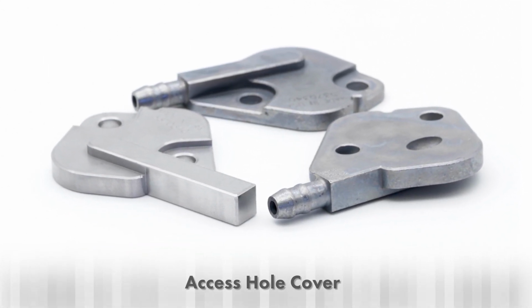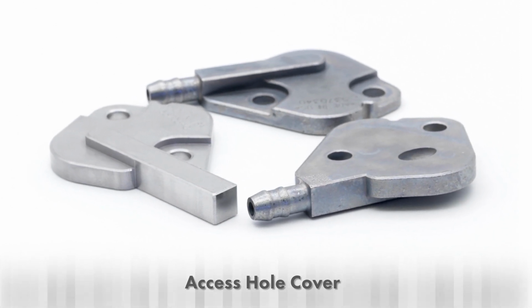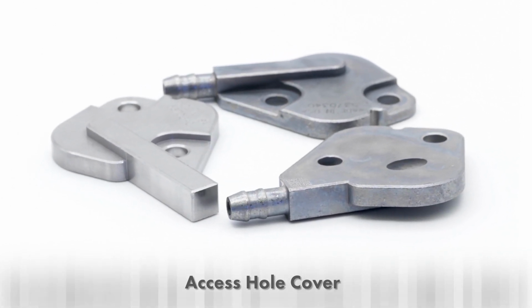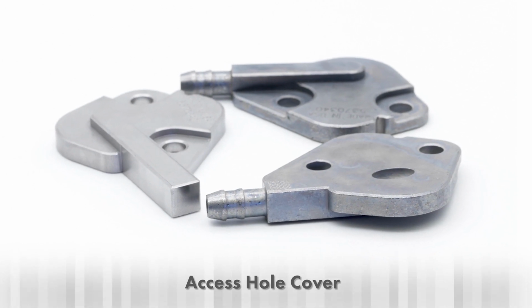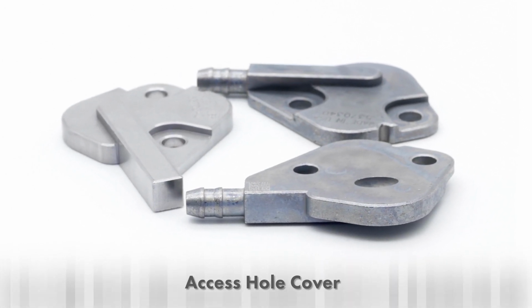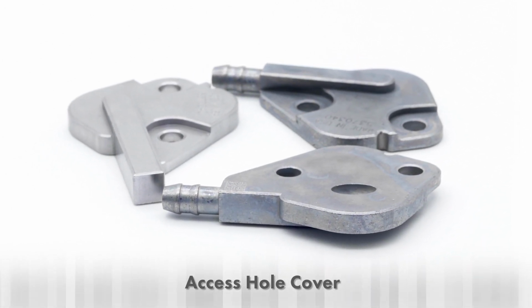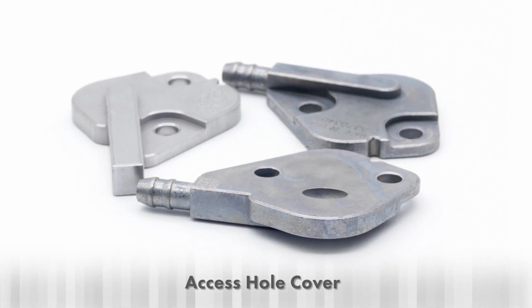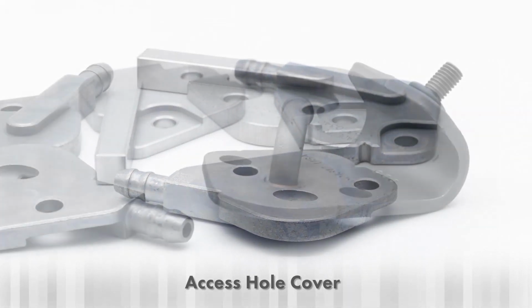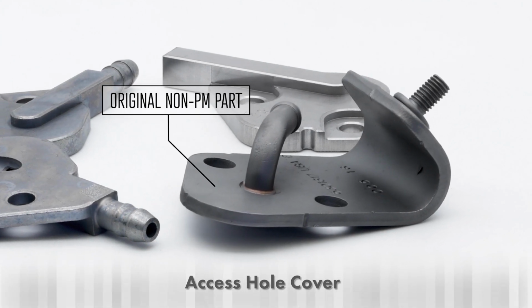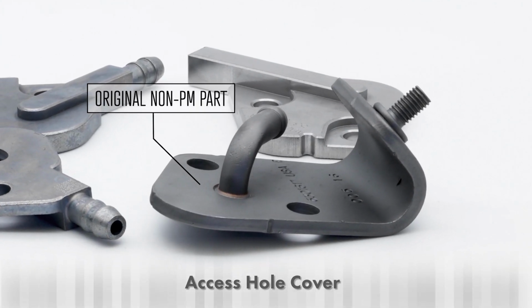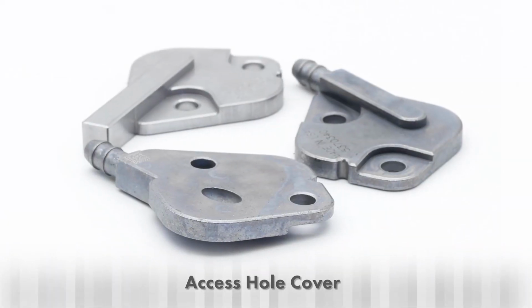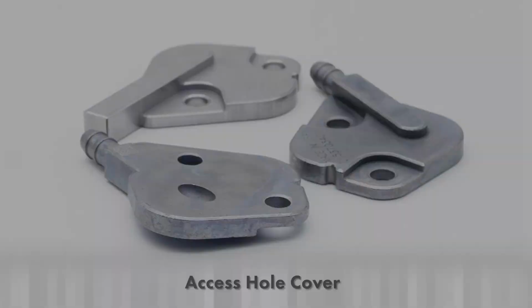After machining, the part is zinc-nickel barrel plated and washed. The 14:1 length to diameter ratio of the 5mm partial through hole presented a challenge and required a lathe equipped with a Y-axis for deburring the hole where it broke through the ellipsoid profile. The PM part replaced an assembly of multiple stamped, machined, and drawn components and resulted in a 27% weight savings.